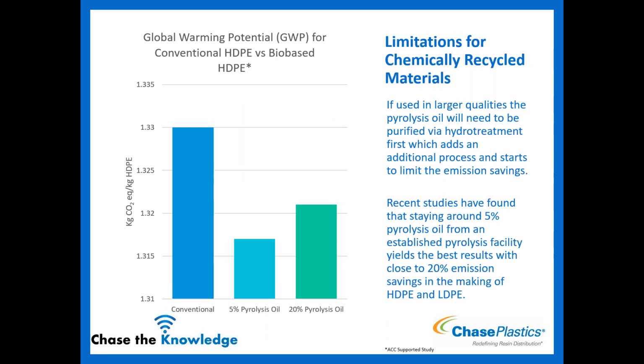Okay. And so some notes to that or things to look for is that if you're using this oil in a really large quantity, so let's say you get a bunch out and then you want to introduce it at a certain percentage compared to the other oils that we're using, if you use it over a certain amount, generally about 20%, you have to purify it. And so the idea is your chemical recycling is already a little limited in terms of the amount of savings you get for greenhouse gas emissions. So you get less, it is less than your standard conventional, but if you start using a lot of oil and it has to go through an additional process, now you're starting to create another emission, or there's more emissions being done because of the new process. So you actually start to see a limitation. You still generally see an improvement overall, but just keep that in mind that there might be a reason why there's only a certain percentage of green in your product, and it might be because of this specifically.